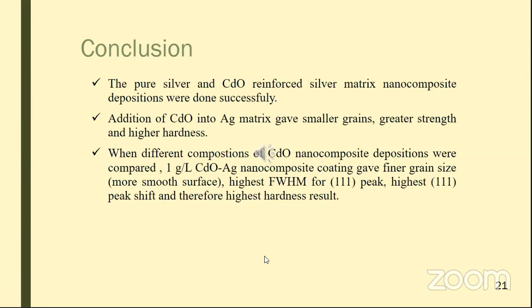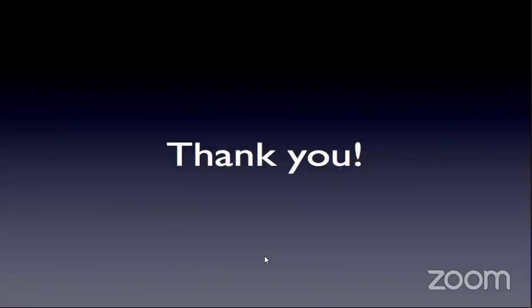When different compositions of cadmium oxide nanocomposite depositions were compared, the 1 gram per liter cadmium oxide silver nanocomposite coating gave finer grain size, a smoother surface, the highest full width half maximum for the 111 peak, the highest 111 peak shift, and therefore the highest hardness result. Thank you for listening to me.